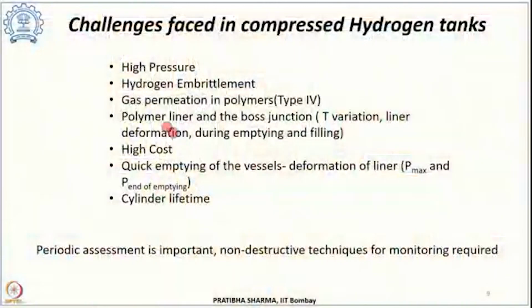But the major challenges in the materials selection in a compressed hydrogen tank are, since we are dealing with very high pressures, that too with hydrogen, which is a very small molecule, diffuses very fast. So the choice of materials, the design of the tanks becomes very important. At the same time, hydrogen embrittlement we know is the biggest challenge when dealing with hydrogen. When we are using polymers, like in type 4 tanks, gas permeation is another important factor that we need to consider.